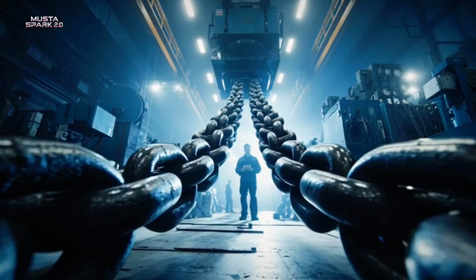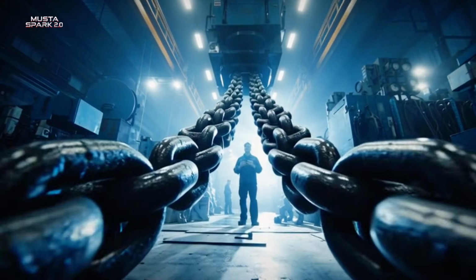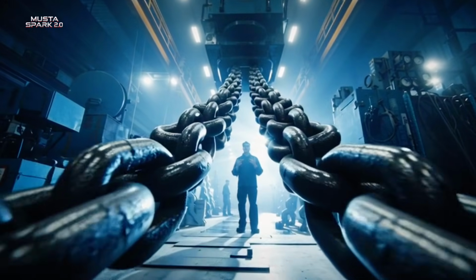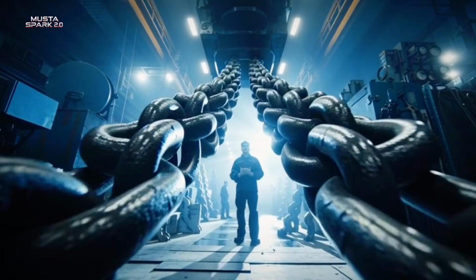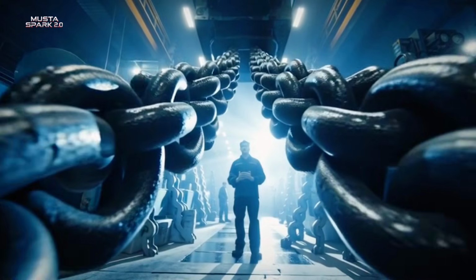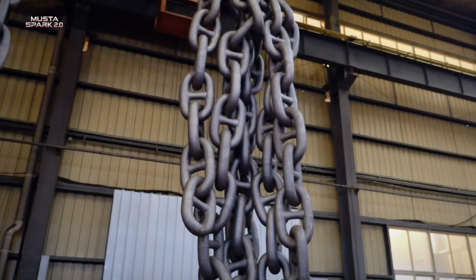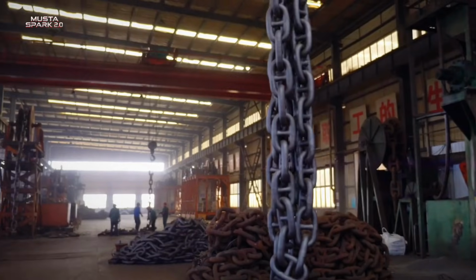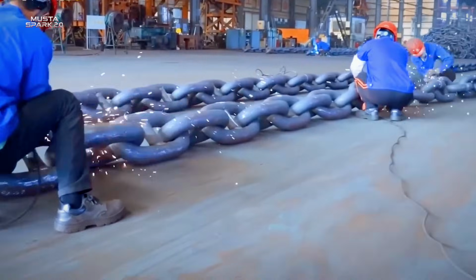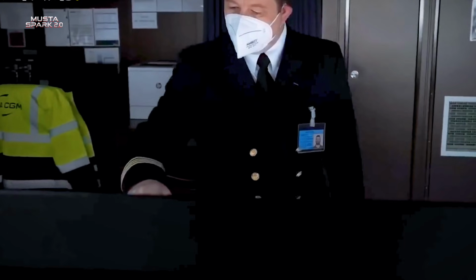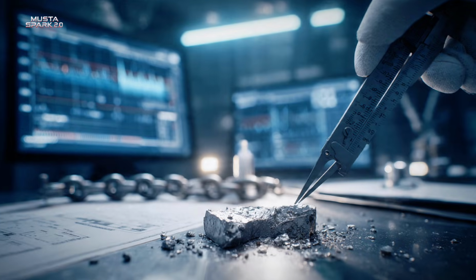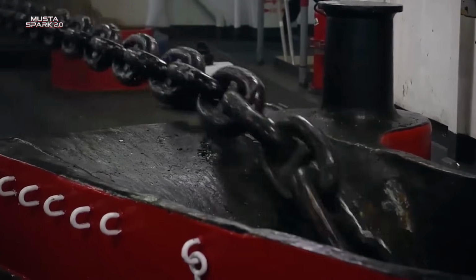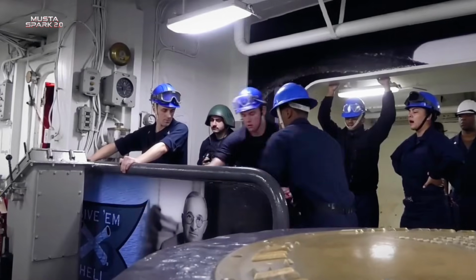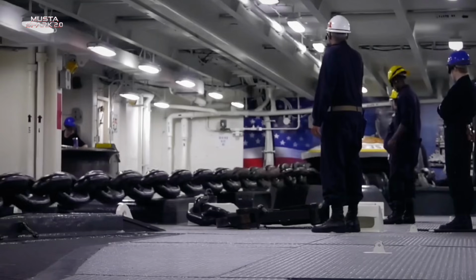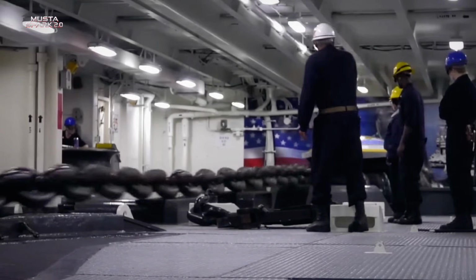For every batch of chain produced, a sample must also undergo the breaking load test, pushed all the way until it actually fractures. This is destructive testing, and those sample lengths are sacrificed for data. Engineers measure where the break occurs, how the material fails, what the actual breaking force was compared to the specified minimum. This data goes back into process refinement, quality control records, and the traceability documentation that follows the chain for